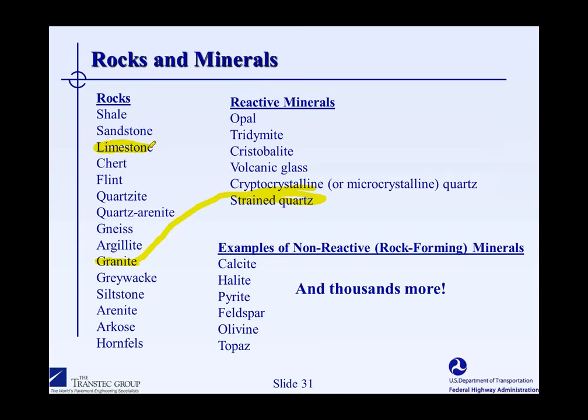Another good example is limestone. Limestone is called limestone when you have a rock which is predominantly calcite, and calcite is a non-reactive mineral. So generally, limestones could be considered to be non-reactive. But limestones can contain 5, 10, 15, 20% of other minerals apart from calcite. And there are some limestones out there that contain small amounts of opaline silica, cryptocrystalline silica that's actually in sufficient quantity to make that limestone reactive.